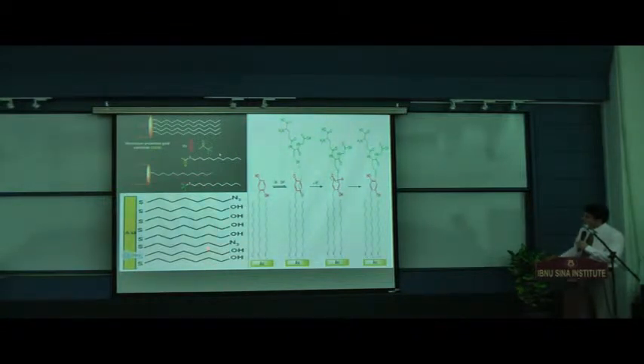Also, we were able to play with the tail group all attached to the surface of gold electrode and do some organic reaction. Here, you can oxidize hydroquinone terminal group to this quinone, and then you have glutathione here. You can easily attach it through Michael addition reaction. Even you can measure the loading amount with the help of electrochemical techniques.